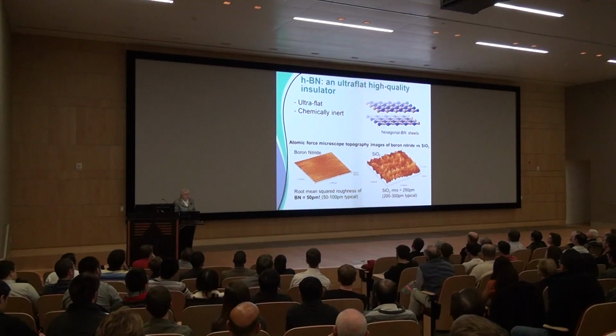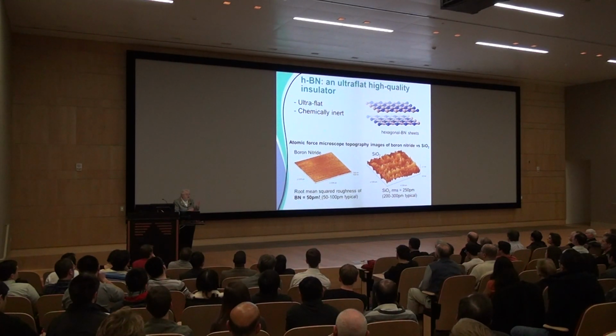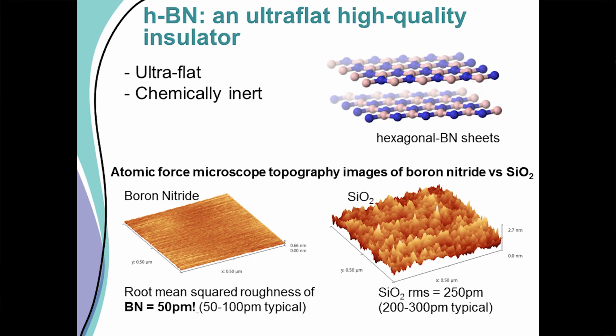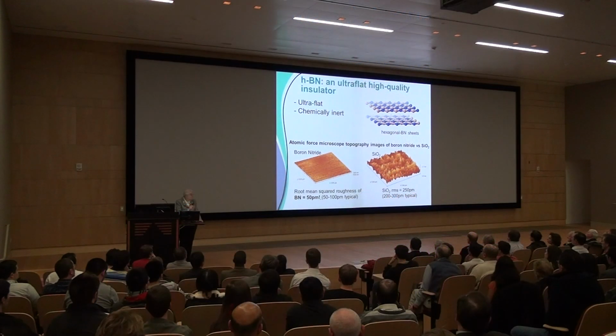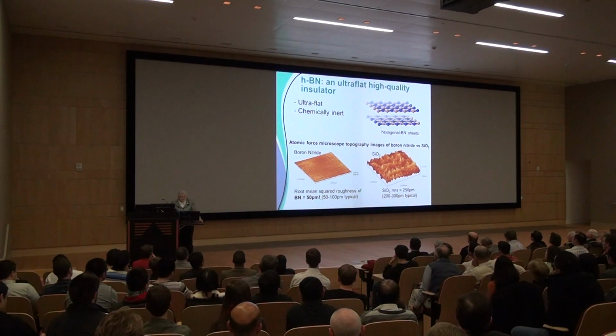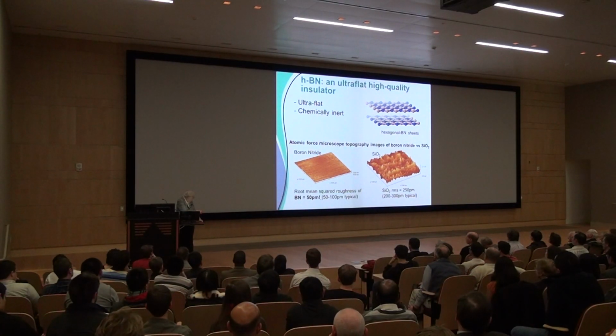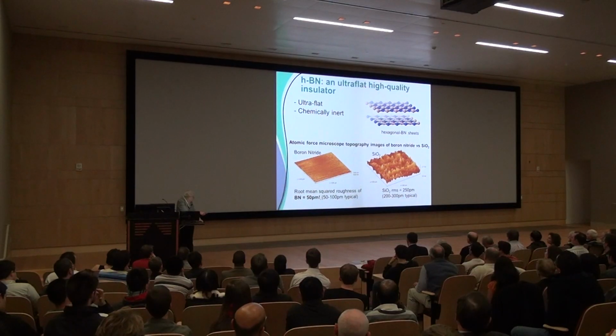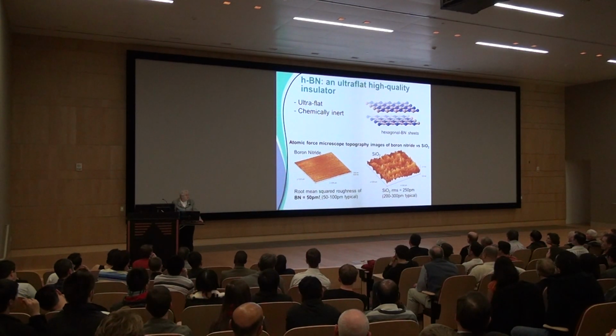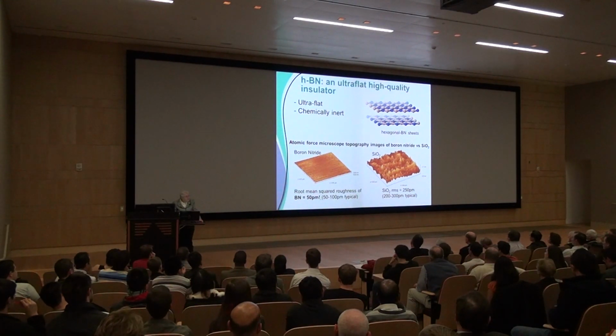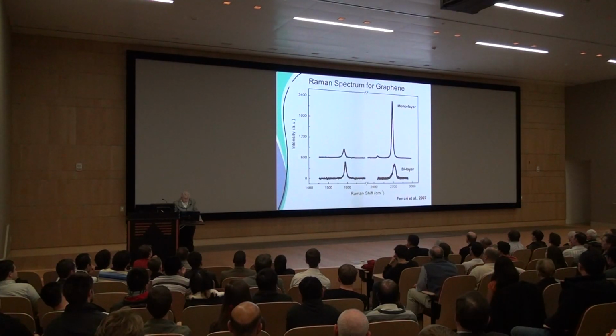The sister to carbon, graphene, is boron nitride. B is column 3, N is column 5, carbon is column 4. So BN is a sort of combination of the two, and the lattice constant in boron nitride is almost identical with that of graphene. So it has many interesting properties, and when you make a layered compound, it's very flat, as shown in this viewgraph here on the left, compared to the SiO2. We like SiO2. That's the mother of the semiconductor industry, so we have to work with that, and we love it. But you see it's kind of a rough surface. So for science, BN is interesting, and for practical applications, SiO2 is interesting.